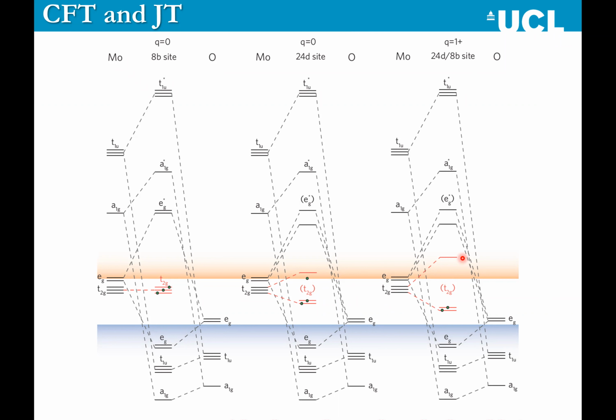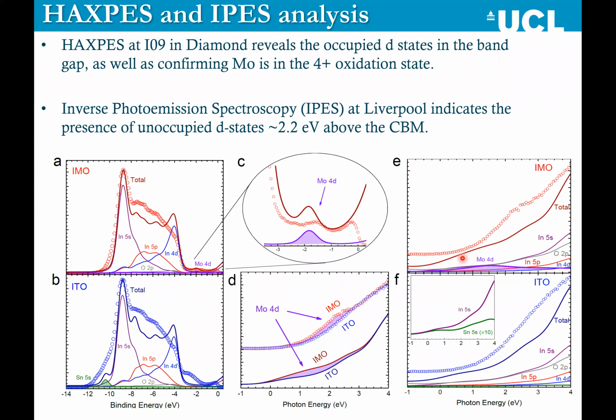But was this the real picture, or is this just an artifact of the level of theory that we're using, or did we make a mistake in the calculations? Could we believe our results? So we took the samples of molybdenum doped indium oxide and we went to our friends in I09 at Diamond Light Source. So I09 is the soft XPS and hard XPS beamline. We did our XPS measurements, and they clearly showed occupied D states in the band gap, confirming our calculations and confirming that molybdenum was in the 4+ oxidation state.